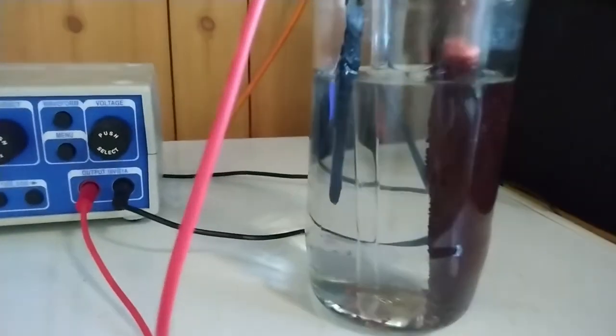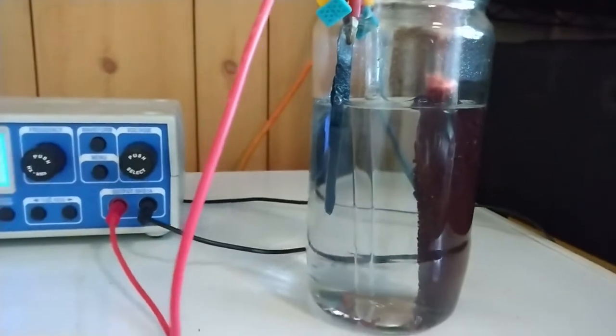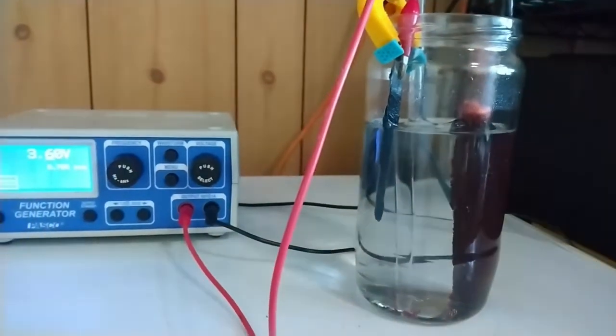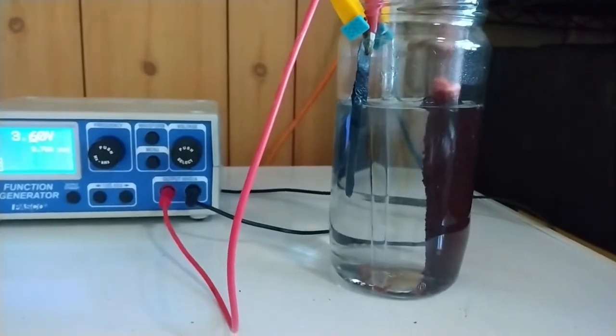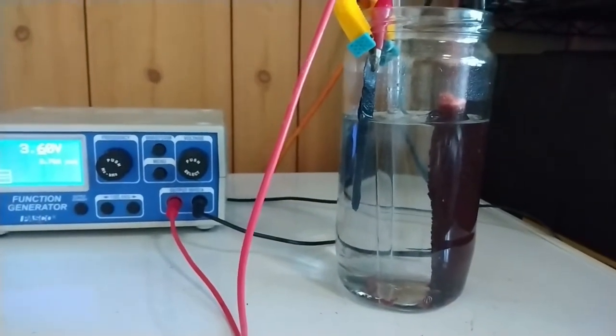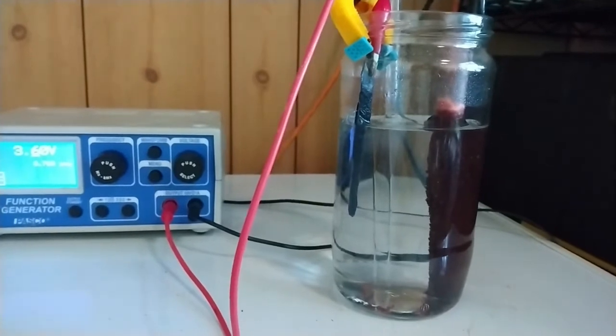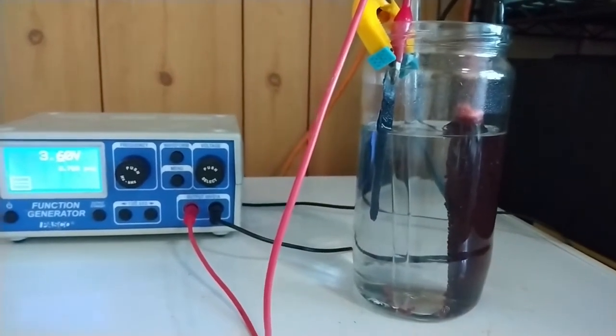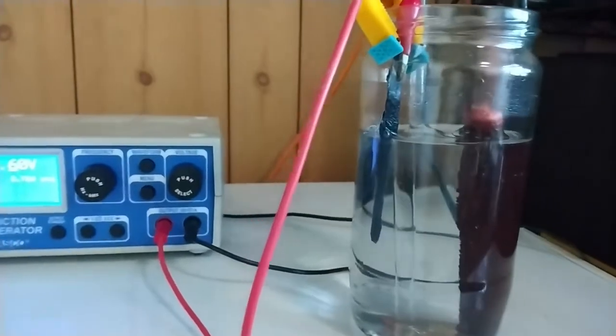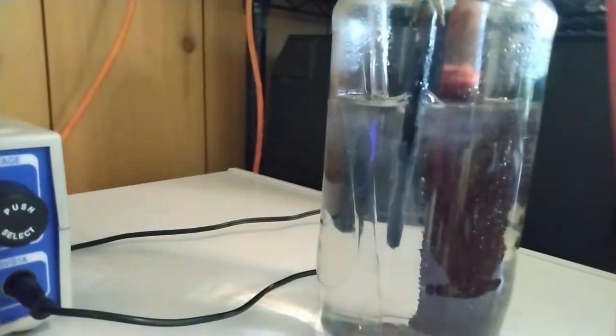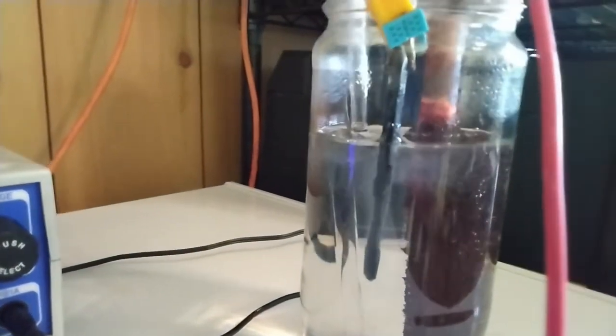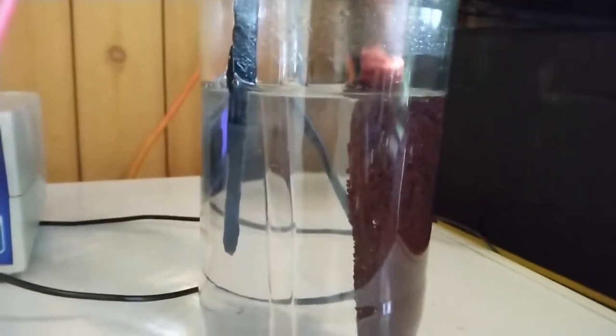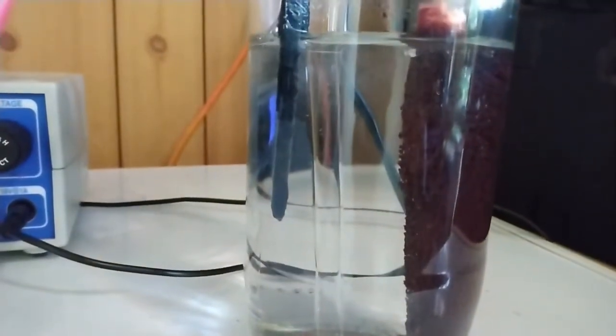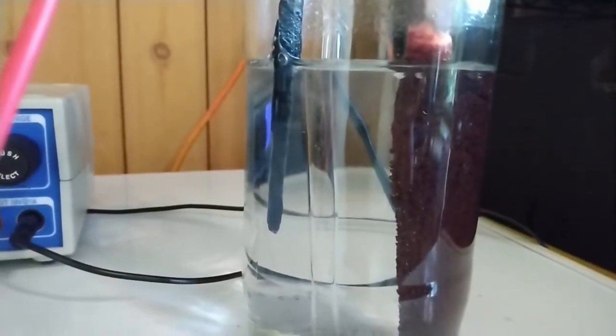So now the solution is completely clear, and well, it took about 24 hours, but just to make sure that there is no copper sulfate left, I left it for 12 hours more, so that's a total of 36 hours. Now you can see that we still have those bubbles at the anode, so that's oxygen. But now that there is no more copper at the cathode, you can see that it also bubbles hydrogen.